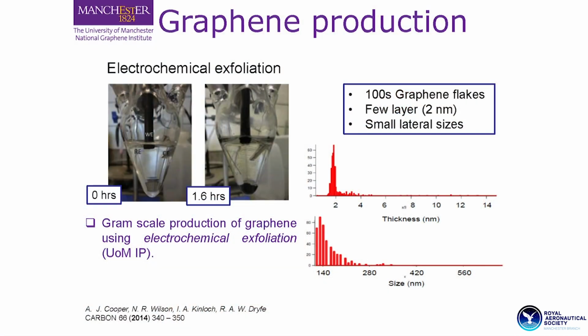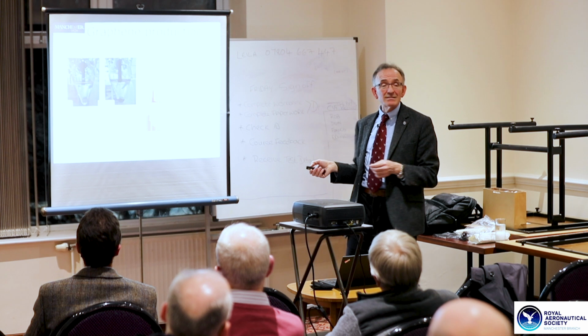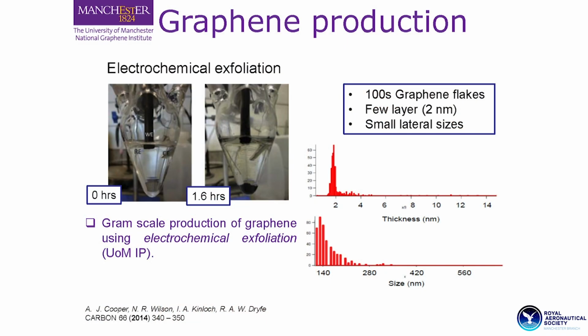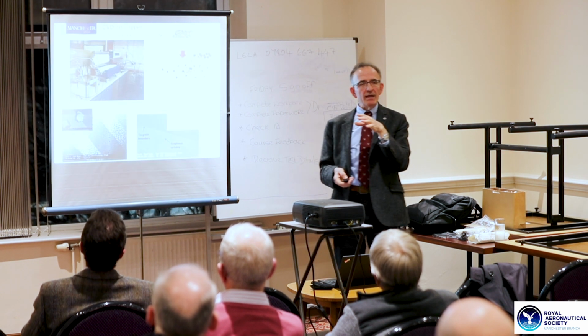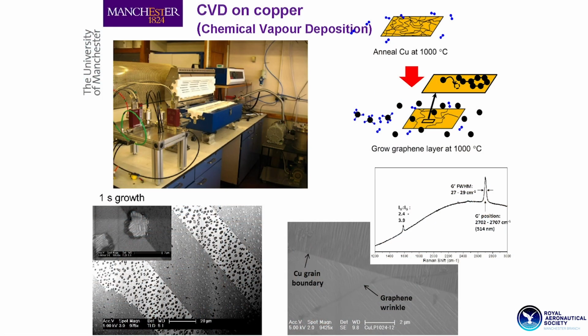So we can do the electrochemical exfoliation. This is a method developed at the University of Manchester. Gram-scale production of graphene using electrochemical exfoliation. The Nobel laureates, of course, they used the Scotch tape exfoliation technique. They took sellotape and they started removing. And luckily enough, they were successful and they received the Nobel Prize for Physics in 2010. So you get hundreds of graphene flakes, a few layers thick, but they come with variable sizes and variable thicknesses. And that might affect, of course, performance. And the other way is with chemical vapor deposition, where you have a substrate of copper, annealed copper at 1,000 degrees Celsius, and you grow graphene layer, atom by atom, at 1,000 C.